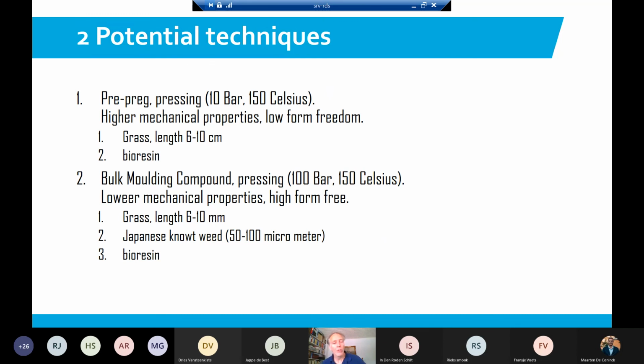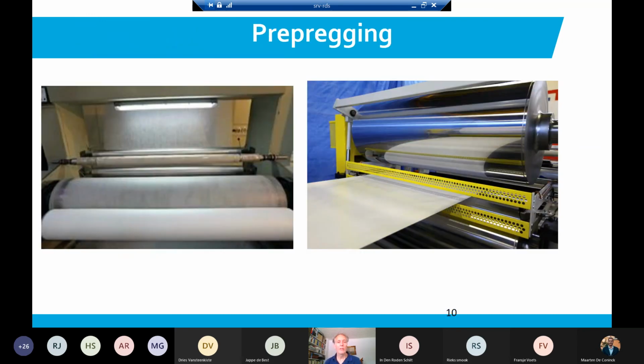this because this is also a waste material and it's pretty hard material. You need, as a filler in this technique, a hard material. So in the facade I showed it was calcium carbonate, and here we replace it by Japanese knotweed, which we also mill to very small diameter. Then we combine it with the resin. We make a dough, and we can compress the dough into a product.